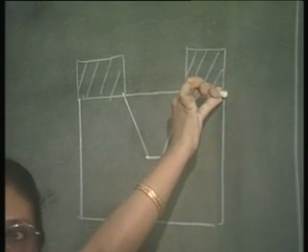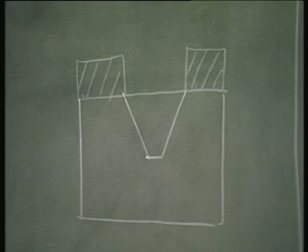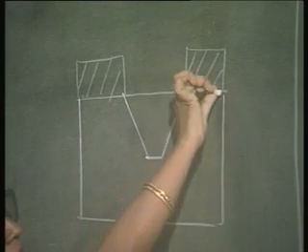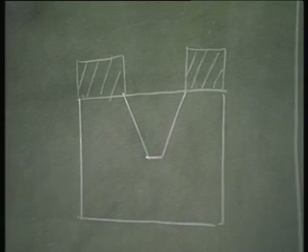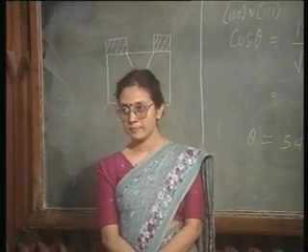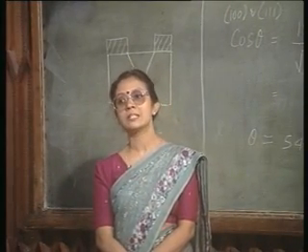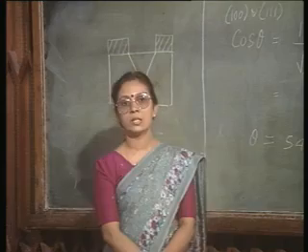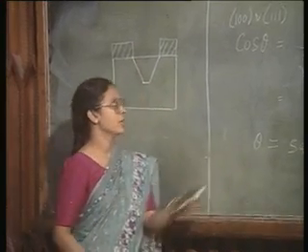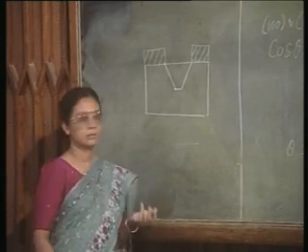54.74 degrees. Do you realize this surface is actually my 100 plane, and what I have exposed is the 111 plane. So, this 111 plane meets the 100 plane at the surface at an angle of 54.74 degrees. So, you see there are some very interesting facts associated with these properties of the 100 and the 111 planes. First of all, if I continue the etching, finally what I am going to have is